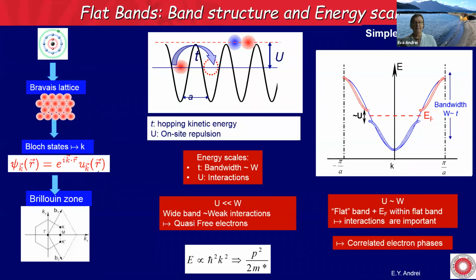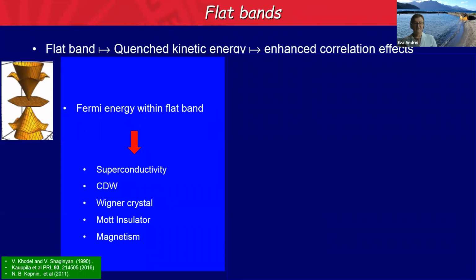For example, in this flat band, because the kinetic energy is quenched, the Coulomb energy can determine the electronic properties, and there are all sorts of correlated states that we can get and imagine: superconductivity, charge density wave, Wigner crystal, Mott insulator, and magnetism, and more. One very interesting prediction that was made by the Finnish group here is that if you have superconductivity in a flat band, it is possible to achieve room temperature superconductivity. This is a very intriguing and possibly controversial prediction, but it would be something that is worth pursuing.